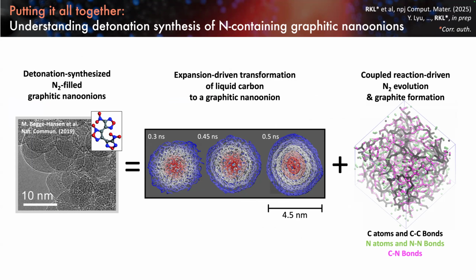But the point is, they are not perfect. What I mean by that is there will be defects in some of the layers that will cause a connection between the different layers. But I would say as a rule, they don't need to be like that. It's more a function of when the particle nucleates in the liquid phase, there is just some number of atoms in that particle. And when you quench, it's going to do its best to form these layers with the number of carbon atoms that it has, but there might be more than it needs. Let's say for the radius, it would want to have 5 layers, but there are some extra carbon atoms.